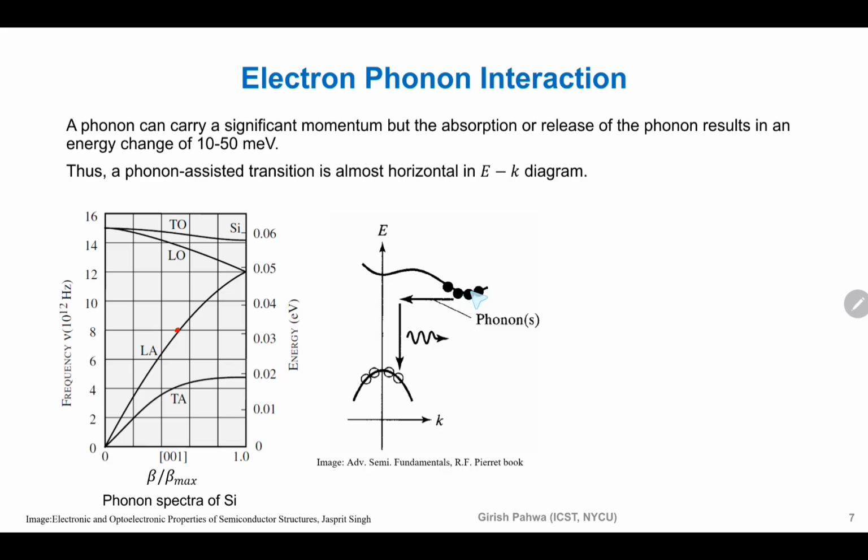So this electron, if it wants to do this band to band transition, means there cannot be an involvement of any traps or anything like that. Any mid gap states won't be there. Photon or phonon can be there, but no mid gap states. So for that, what does it do? We know that photon cannot be directly emitted because it cannot change the momentum, but phonon can. So first electron interacts with a phonon that changes its momentum to a smaller value of K.